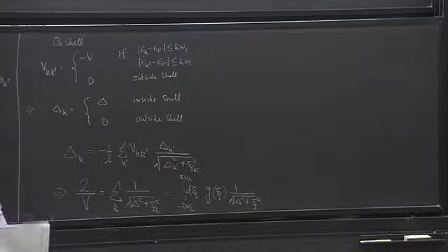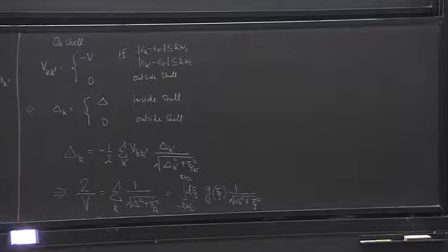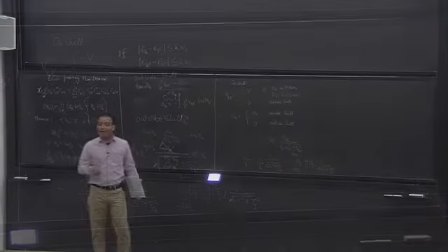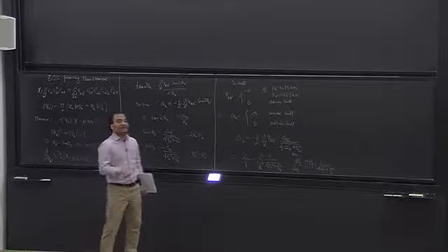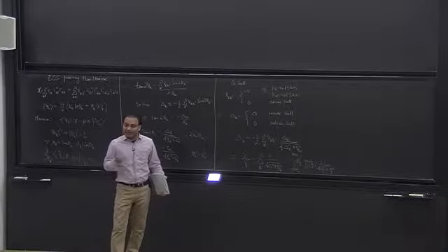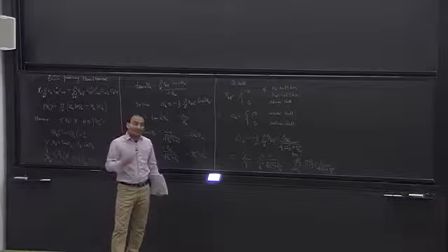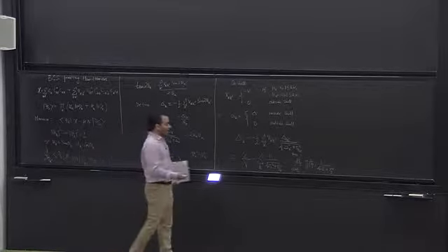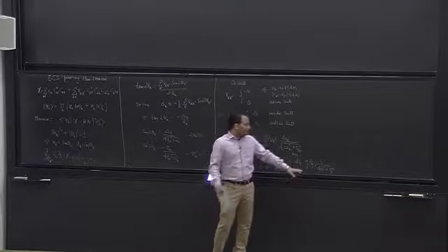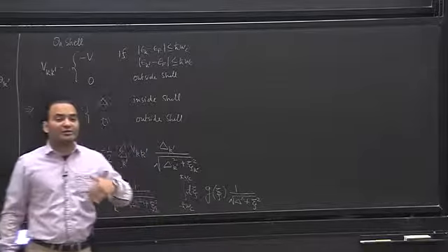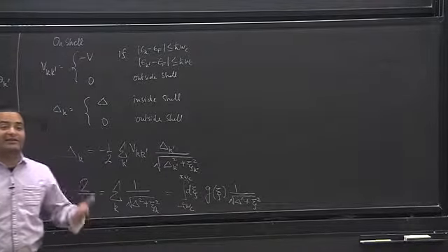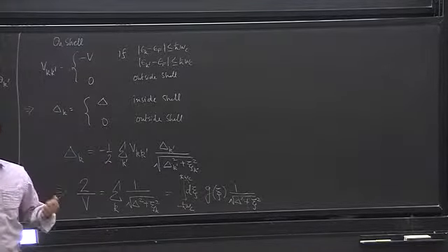Now again, I'm going to assume that the energy scale ħω_c, that is the energy scale where we have attractive interactions between electrons, is much smaller than the Fermi energy. And with this approximation, I would assume that the density of states does not vary much at the energy scale of ħω_c.